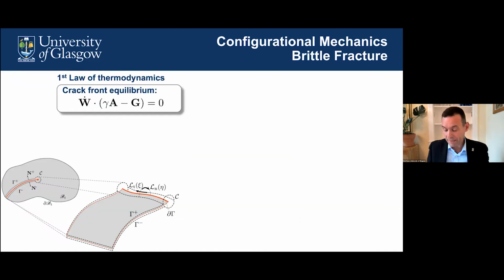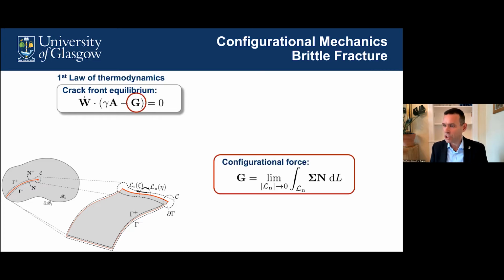Without going into a huge amount of detail around the formulation, what we've done is exploit the local form of the first law of thermodynamics to provide us with an expression for equilibrium of the crack front. And that's given by this equation here. Very briefly, G is the so-called configurational force, sometimes called the material force. And it is essentially the integral of the Eshelby stress around the crack front.